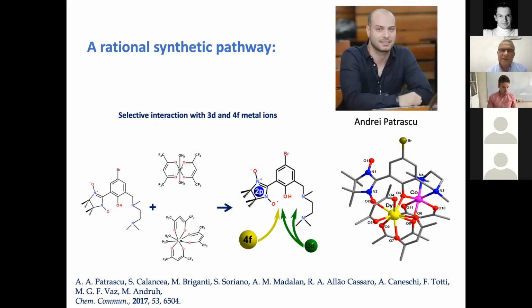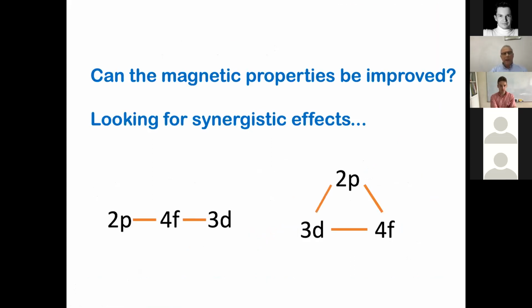So we designed a rational synthetic approach towards such systems. And this is based on our former experience in employing compartmental ligands. I already presented this part 3 years ago in Astrakhan, so I will not insist very much on all the data which are already published. But I only want to mention this strategy allows us to obtain strictly binuclear compounds because we have 2 different compartments, each compartment able to accommodate one type of metal ion, 4f and 3d. So unfortunately, the resulting topology is linear.